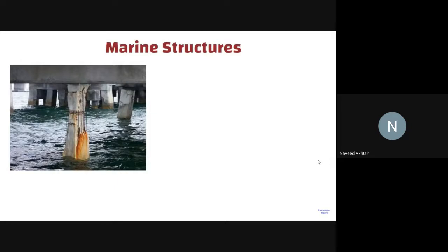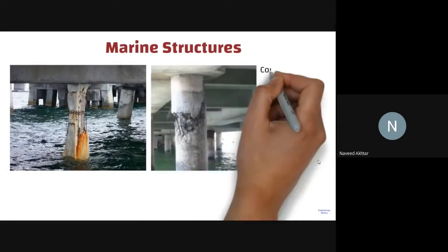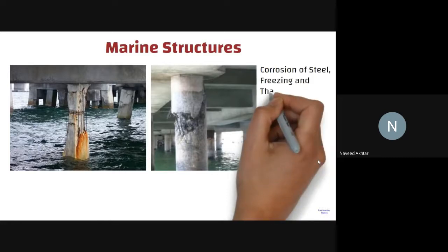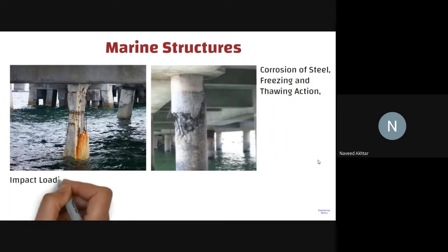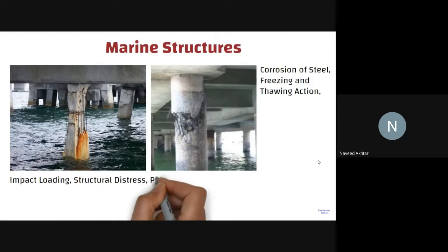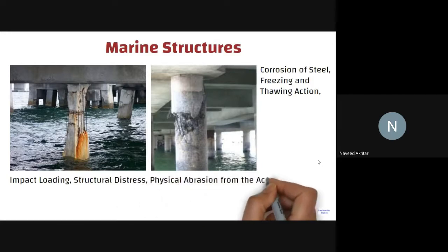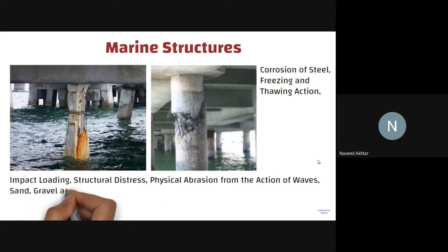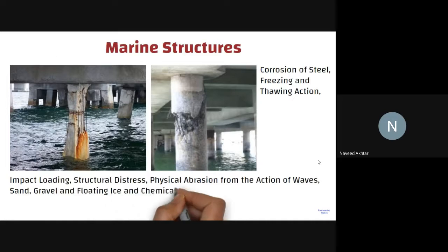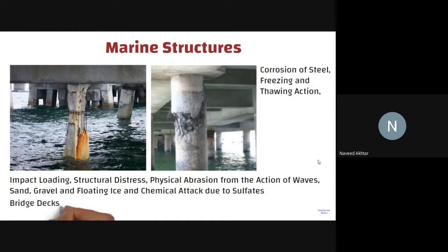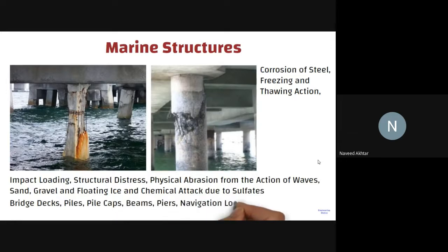You can see the deterioration of concrete in marine structures, and how much distress and physical abrasion from the action of waves there is. There is floating ice and chemical attack due to sulfates. This is the deterioration seen in piers and navigation structures, etc.